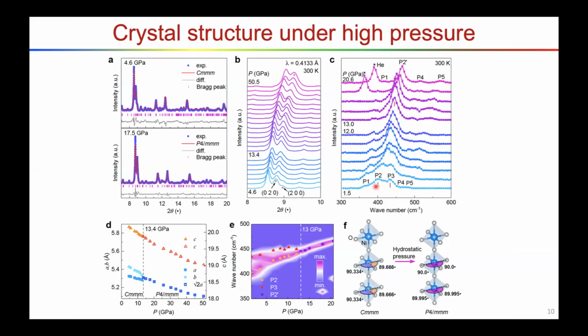With Raman scattering, we can see different phonon branches. Okay, if there's a structure transition, we can also determine the pressure for the structure transition. So this is the wave number of the phonons, and we can also see a structure transition appears at 13 gigapascals. This structure transition corresponds to an orthorhombic to tetragonal transition. Because even at low temperature and ambient pressure, the angle along the c-axis, nickel-oxygen-nickel, is already 180 degrees, but a is not equal to b. When we apply pressure, a will become equal to b. Okay, so that's the structure transition.